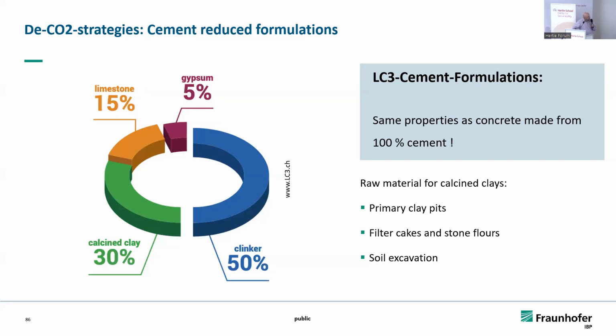And here's one example of a clinker-reduced cement, a so-called LC3 formulation. This stands for limestone calcined clay, and it's a 3-component system. It's a formulation which contains only 50% of cement clinker, 30% of this calcined clay, 15% of limestone. And this gives you a concrete with the same properties as if it would be made from 100% of cement.